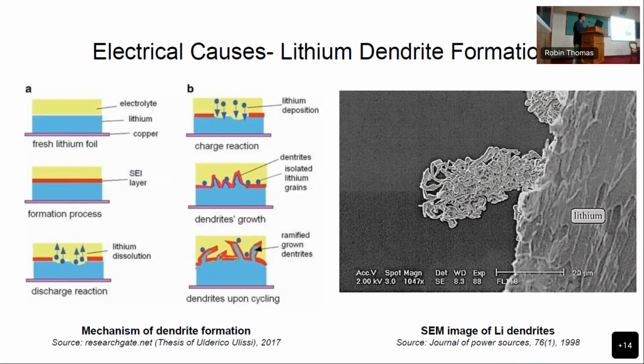When the discharge starts, the lithium is being dislodged from its position, which is the anode, and it is traveling to the cathode. But while charging back, what we'd expect is that the lithium will come back and get deposited in this pattern itself. But that doesn't happen. There is a very irregular deposition of lithium when it is traveling back during the charging process. Due to this irregular deposition, we have small mounds and spikes which serve as nucleation sites for further deposition. So these irregular deposition points propagate further and further, forming needle-like structures, which are the dendrites. Dendrites have the potential to grow so much as to touch the cathode, which will result in short circuiting.